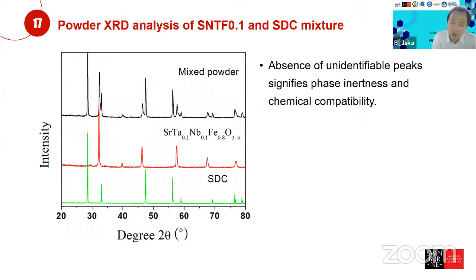Then we also mix the powder SNTF with the SDC, and we subject it to 1000 degrees Celsius. We find that there are no extra peaks that come out, meaning that our materials are quite stable.